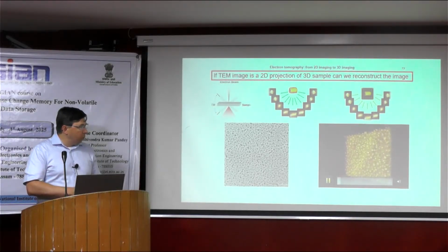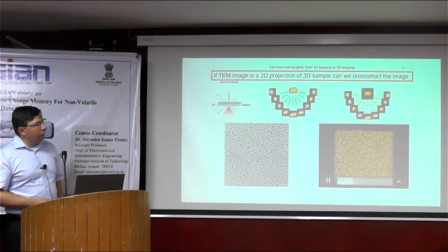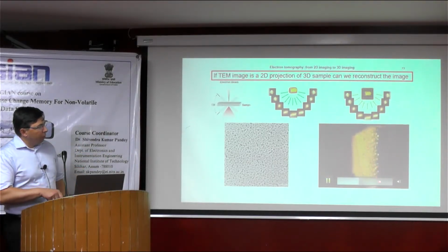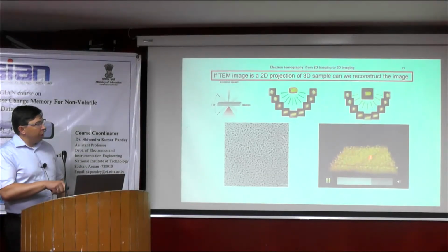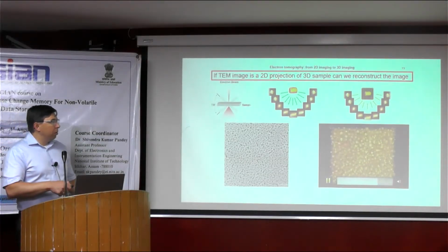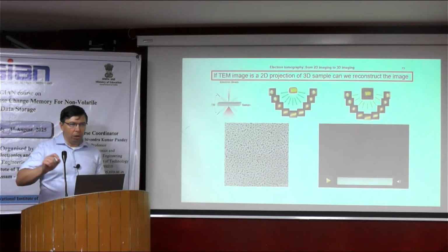So there was no preparation in this case, only the image in tilting, and you can again see that a larger fraction sits on one surface of the sample. And if you have such a 3D image, you can also proceed with quantitative analysis of your images, like you can calculate the sizes and distribution in different places, and also the distances in between.